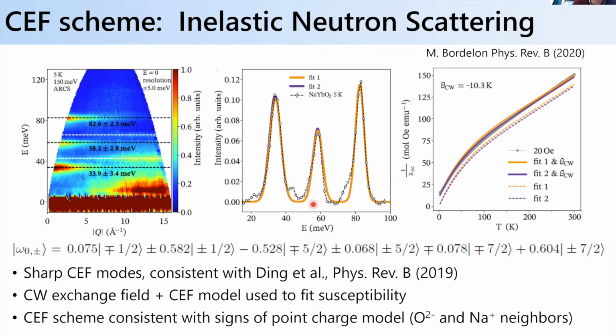So we can take the intensities of these and their relative energies, as well as fitting the magnetic susceptibility as a function of temperature, and we can solve and extract what the ground state doublet is, which we did. I guess the details of the actual ground state doublet are not so important for this particular slide, except to say that the first excited state is pretty far away. It's 33 meV away. So when I show you measurements down below 50 Kelvin or so, we're pretty well into the J effective 1/2 regime. And as well, the other point is that these crystal field excitations are reasonably sharp, meaning they're limited by the resolution of the instrument, which just means that there's not a measurable level of disorder that the local ytterbium 3+ ion sees. Okay, so basically the crystal field seems pretty homogeneous in that regard.